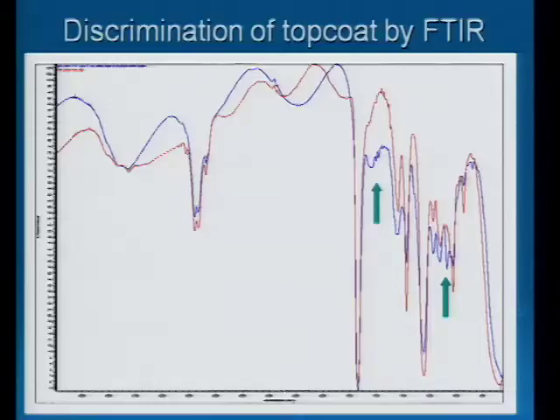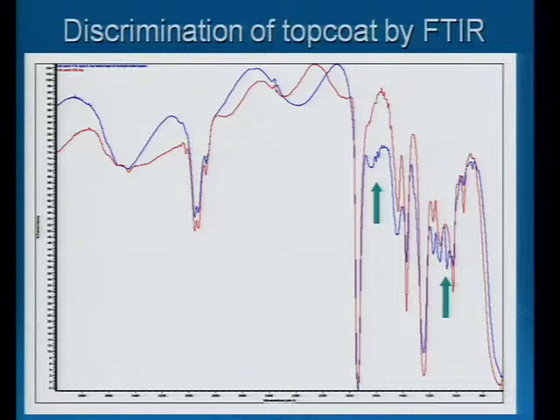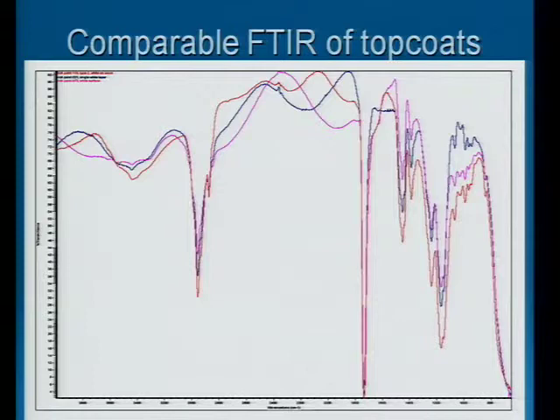We then performed FTIR analysis, and even groups where the samples might look comparable visually, we were able to discriminate based on FTIR of the top coat. There were some where we couldn't discriminate by FTIR, but then doing a visual comparison of the samples in that subset, color did discriminate between samples.